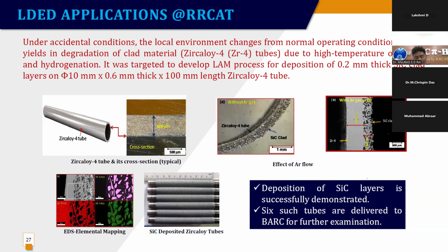Then we came up with a very novel idea of argon flow from inside the tube, a very effective way. This changed the whole scenario, and on the right hand side you see a microstructure where you can clearly see the distinct silicon carbide clad deposit and then zircaloy 4. We could really achieve 200 micron of silicon carbide and then 400 to 500 micron of zircaloy 4. This opened new avenues, changing the overall game, and we are able to make an accident tolerant zircaloy tube fuel bundle with this. This technology will be really attractive in the future to move ahead with.